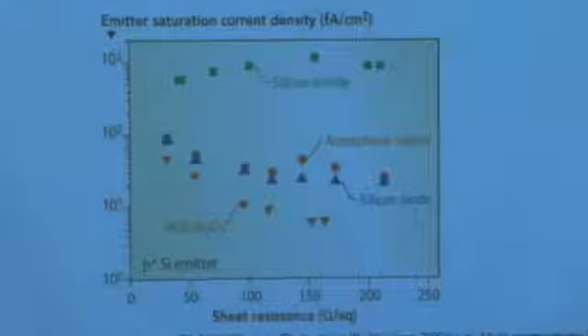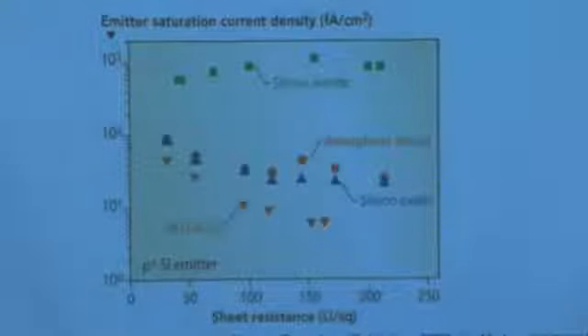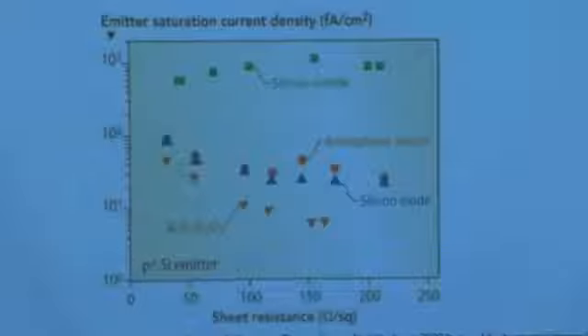devices. In this particular case, they're plotting emitter saturation current density in femtoamps per centimeter squared. This is very, very low. Versus sheet resistance, this is essentially the dopant concentration in the emitter. So they're looking at how the passivation quality changes as a function of dopant density. And silicon oxide works pretty well. And it's an effective diffusion barrier.